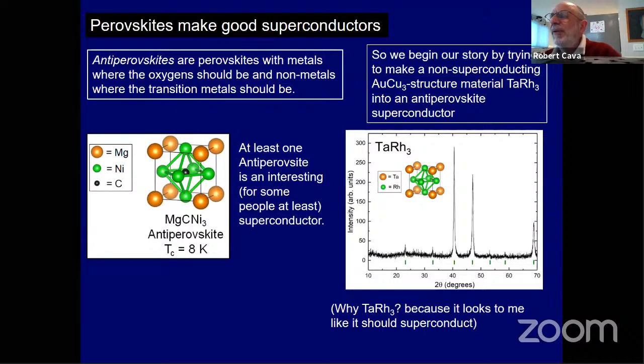So this is an interesting example of what we do for a living and why I find referees so annoying. Basically, here's what happened in this case. Back when MgB2 came to be, I realized that there might be something interesting about magnesium combined with other elements in the periodic table that people don't usually compare it with. And we found this magnesium carbon nickel 3 anti-perovskite. So it's like a perovskite, but nickel is here instead of oxygen, where oxygen is typically. This is nickel. Oh, sorry, duh, stupid me. This green stuff is nickel. So it's where the oxygen is.